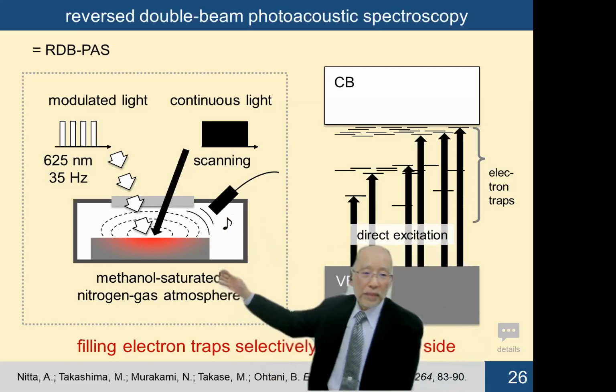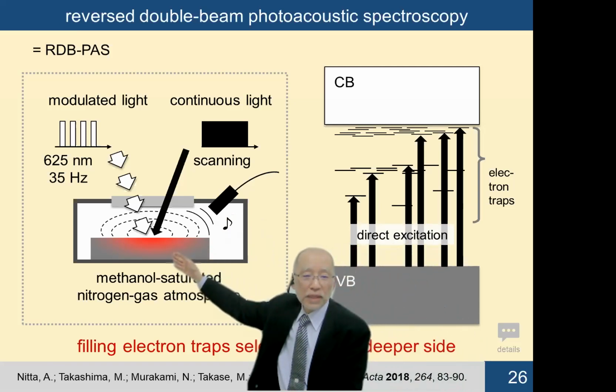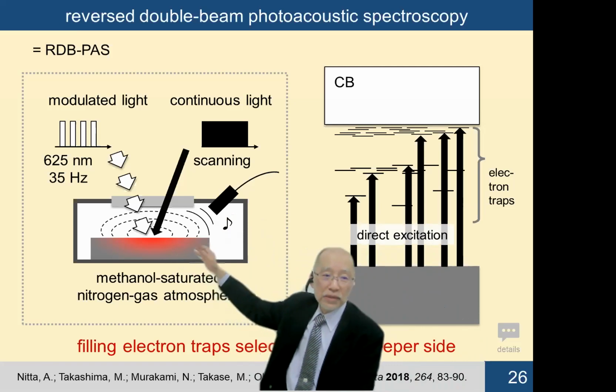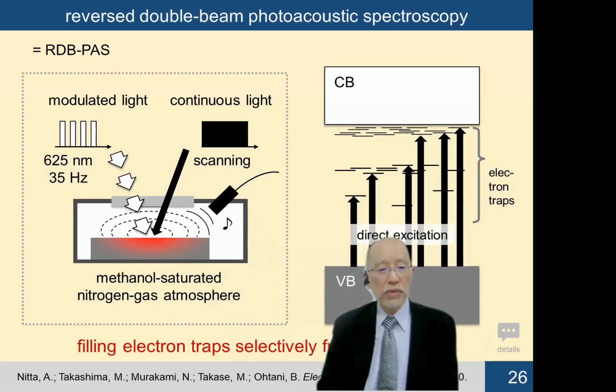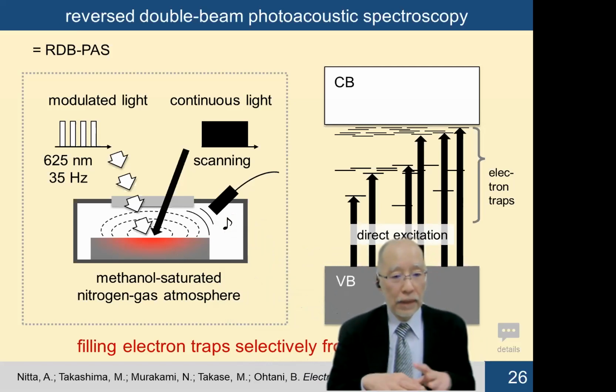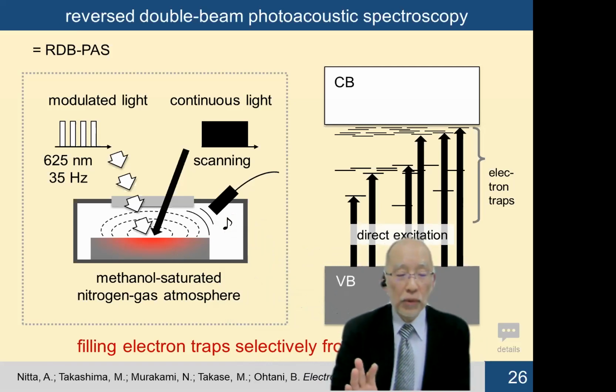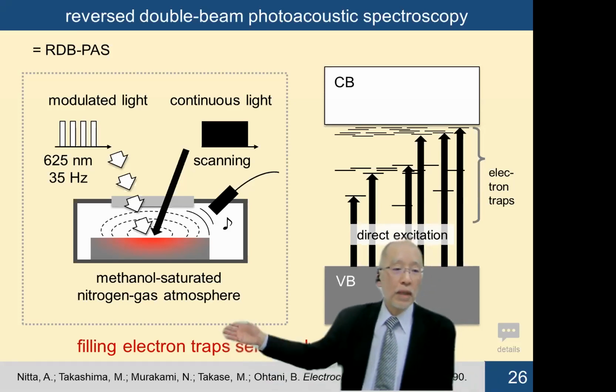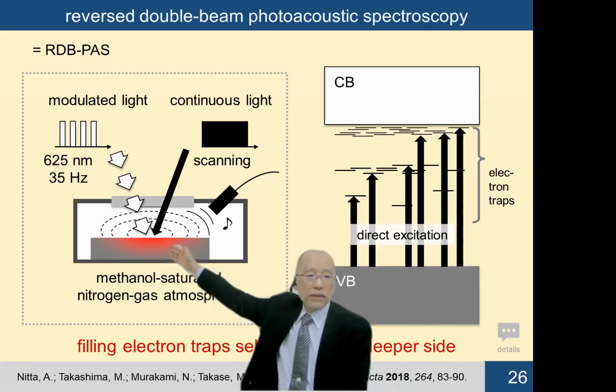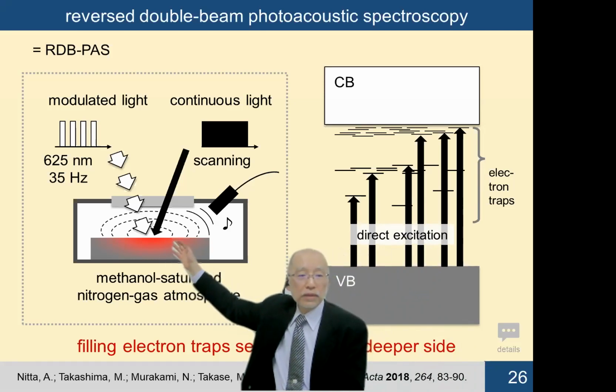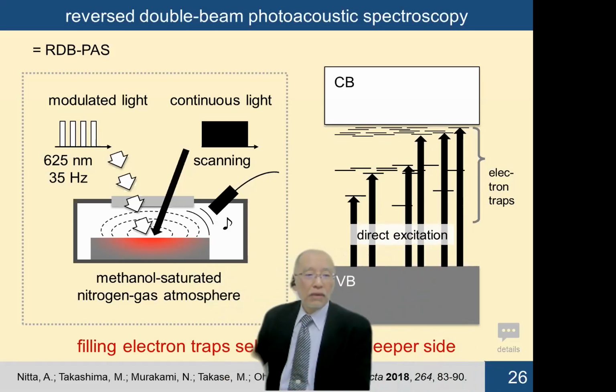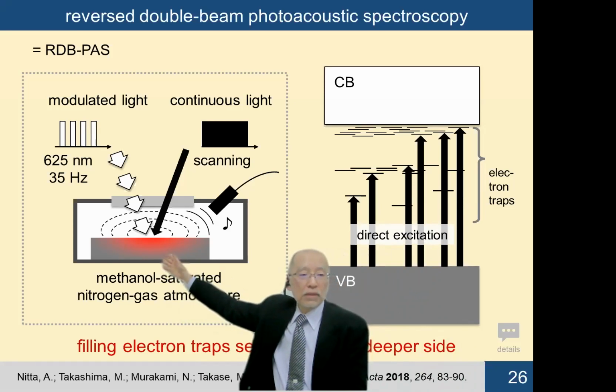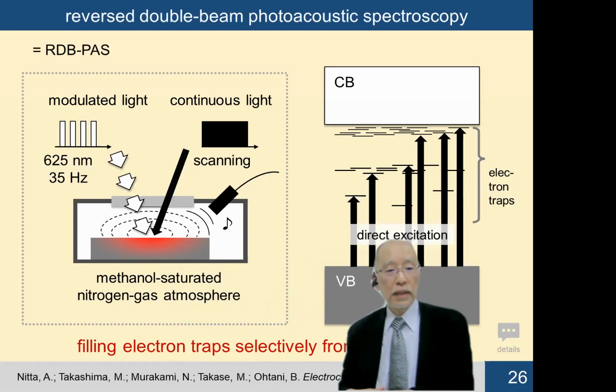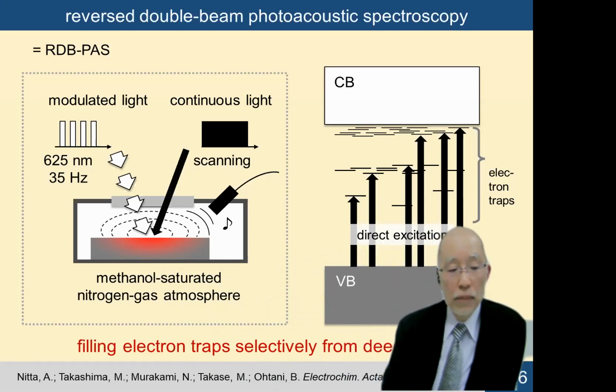And if this sample doesn't absorb light, no signal happens. In ordinary spectroscopy, light that is diffused or reflected without photoabsorption can be detected as apparent absorption. But for PAS measurement, only absorbed light is detected. Even if the light is reflected or diffused, nothing happens. When the material absorbs light, it gives a sound. So that is a very good way to measure solid photoabsorption.